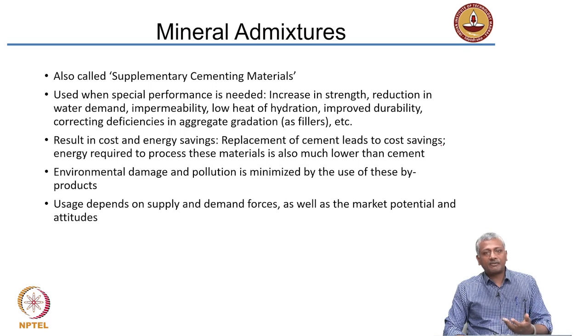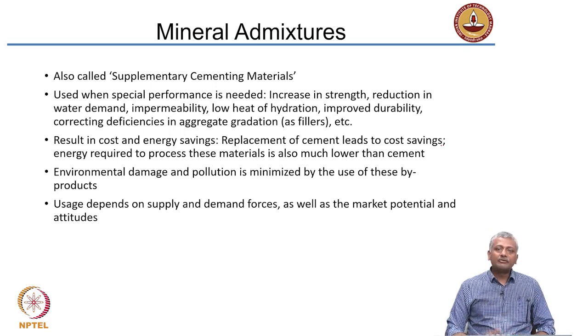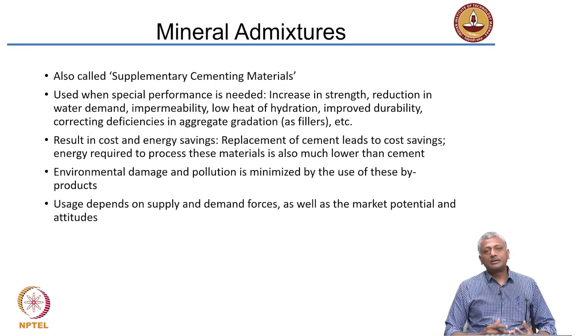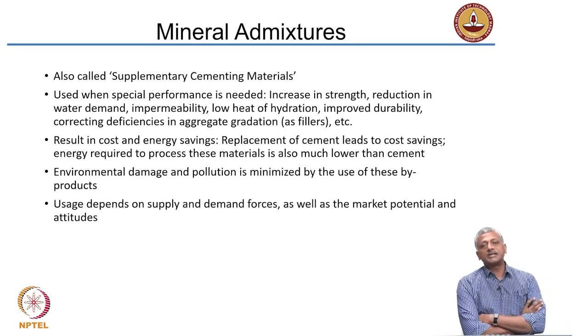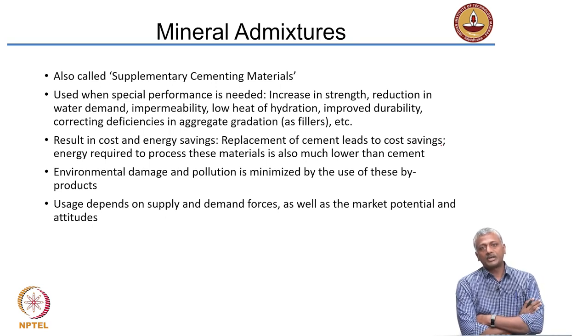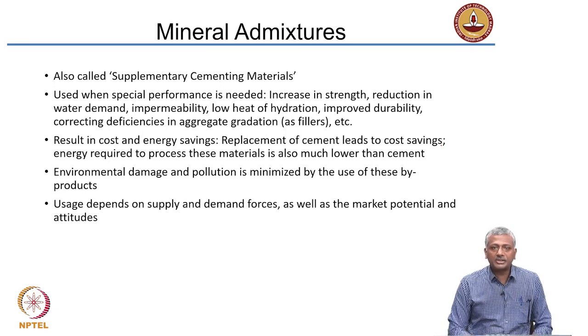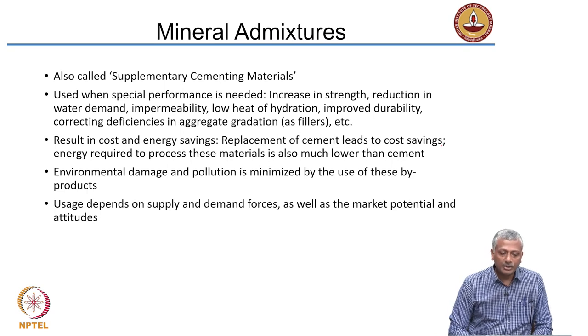When we talked about types of cement, we mentioned Portland pozzolan cement and Portland slag cement. The pozzolan is mostly fly ash — the ash from a thermal power plant which contains some silica in it. That silica reacts with the calcium hydroxide generated during cement hydration to produce additional CSH. This additional CSH helps in improving durability of the concrete.